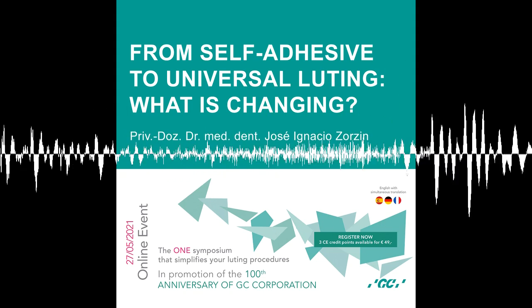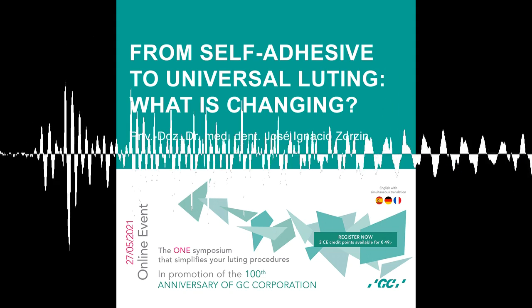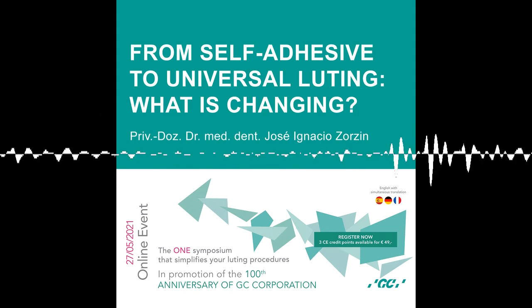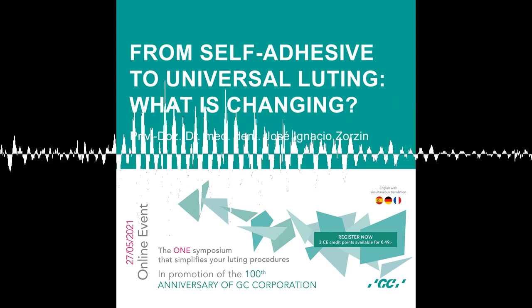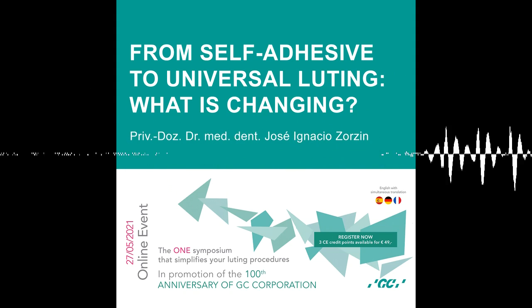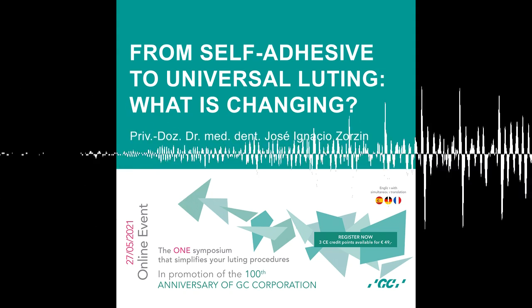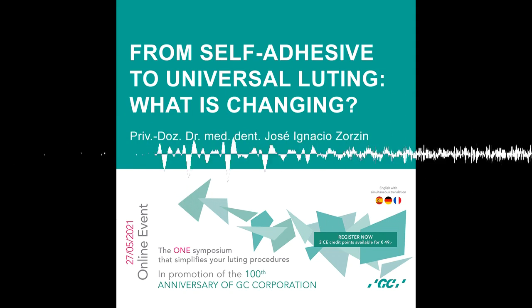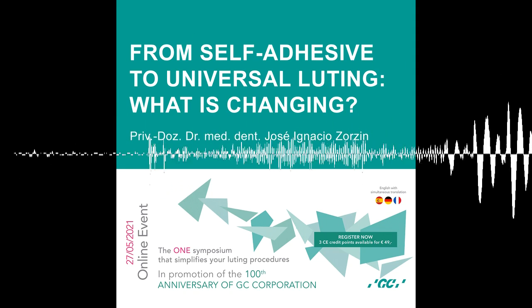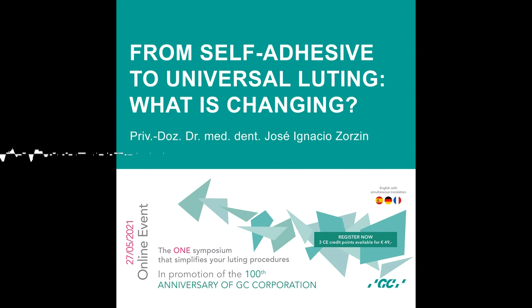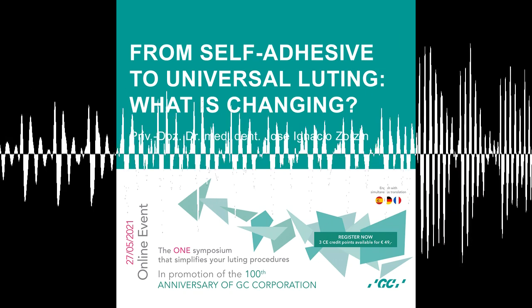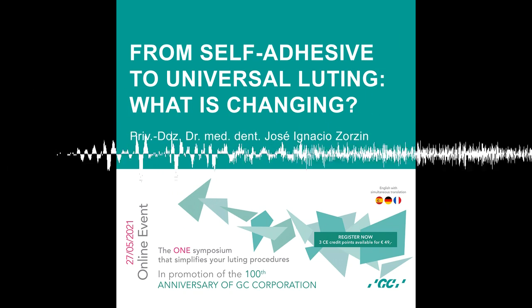Polymerization is a big point. It also depends a little bit on the indications you have. For example, if you want to have something which has to do with a lot of aesthetics, with very thin ceramics, it's maybe better to go for the light cure path, because you always have this fear or this risk of discoloration when you have dark curing systems inside a luting resin.